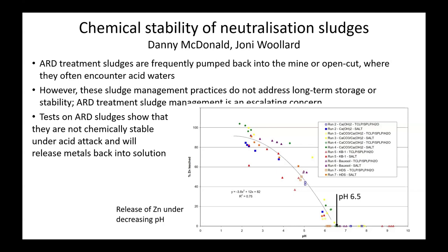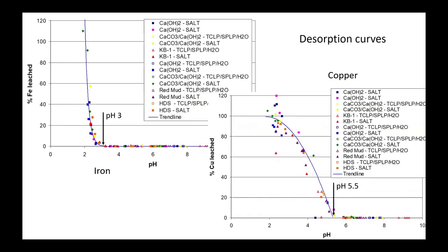So Danny did quite a lot of testing on these, and he showed that as you drop the pH, the metals will start to go back into solution. So you can see in the bottom right there, as you drop the pH to just 6.5, the zinc starts to get released back into solution. And next slide. For copper, once you drop it back below 5.5, the copper starts to go back into solution. And if you drop the pH down to 3, you start to redissolve the iron as well.